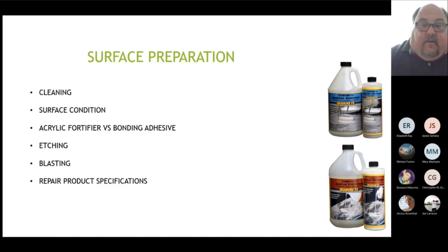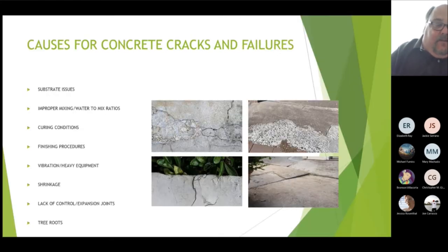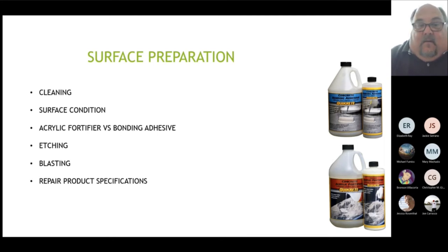The surface condition also is important, just like we saw on the past slide. I'll go back to that. If you're looking at the top left corner, see all those little debris chunks that are getting ready to fall out? It's best to just take them out. You're patching the material anyways. What that's going to cause is an air bubble underneath it. It's going to cause a gap. And when weight's applied to it, it's just going to fracture through to the new patch that you put on top of it. So remove all the loose debris, everything that's not firmly attached to the slab. That's going to help you ensure that you have a good bond.